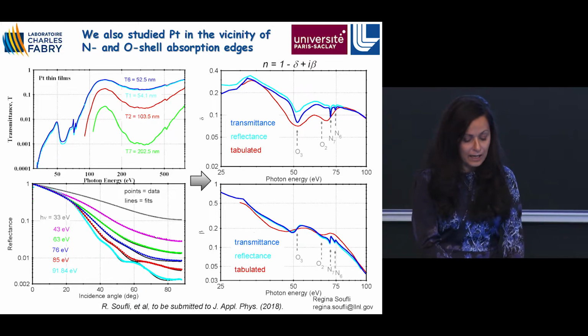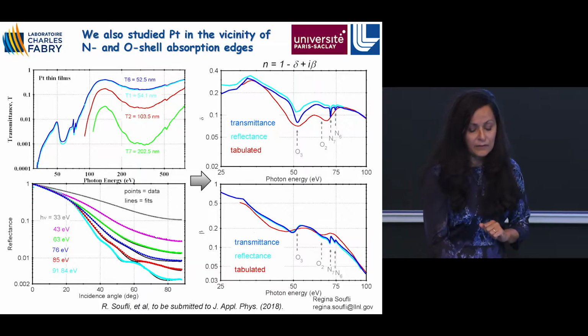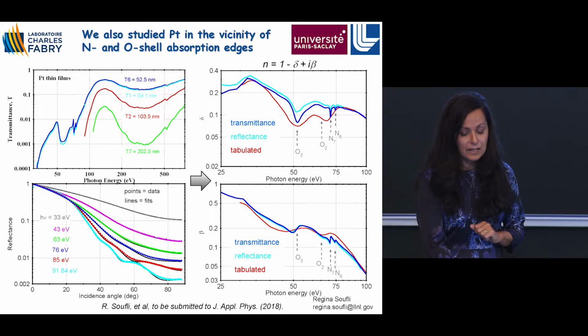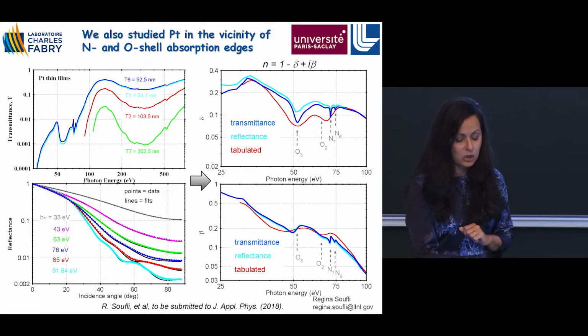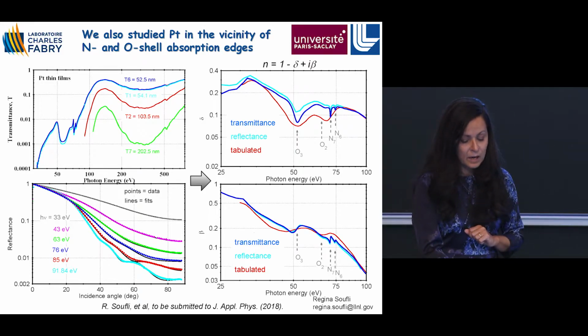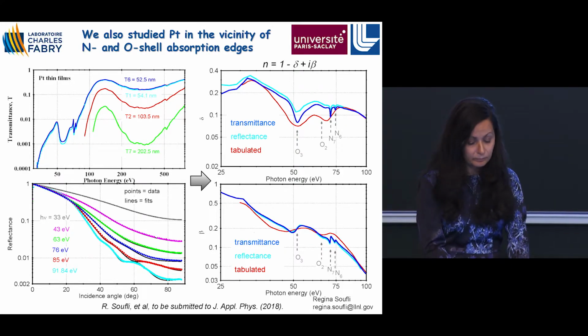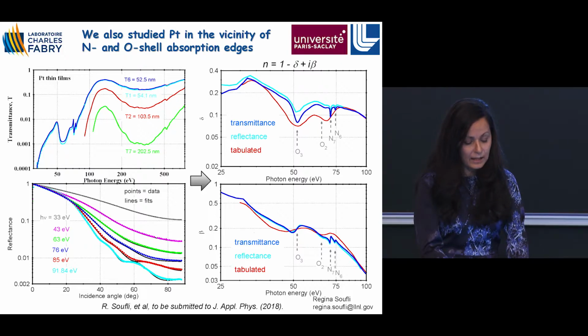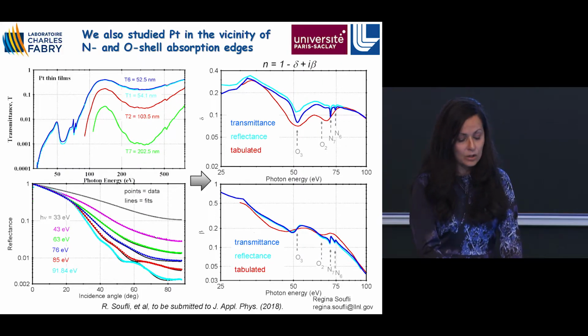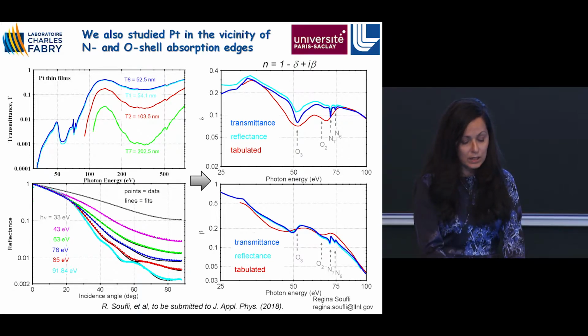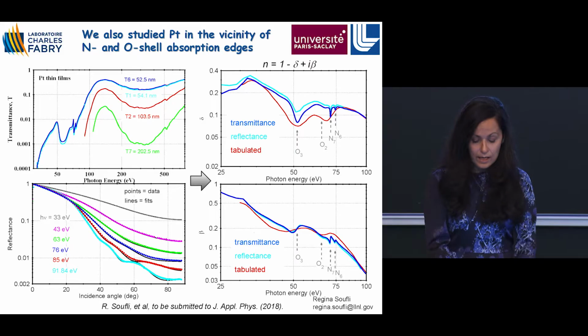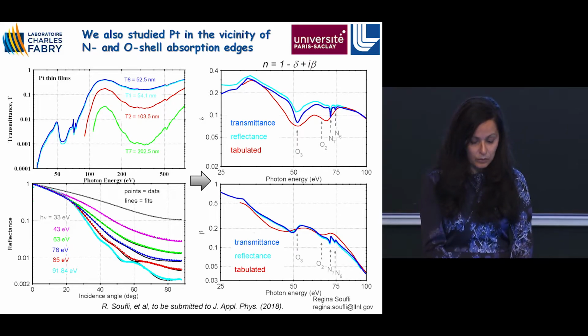And I'm showing here our data again. There is fine structure that was missing. The red curve here is the tabulated values, and you can see the difference and the detail in fine structure that our measurements revealed. This is our measurements by transmittance, the dark blue, and reflectance by light blue. This is the real part, and this is the imaginary part. Again, you have a beautiful resolution of the O and N edges, which did not exist before. And so again, this is ongoing work that we're doing.